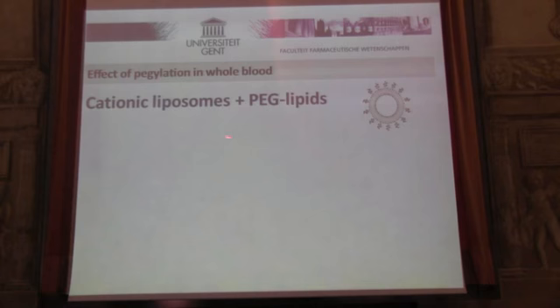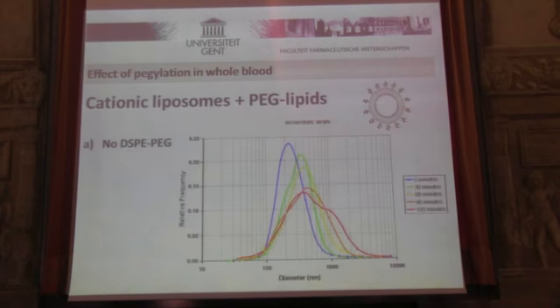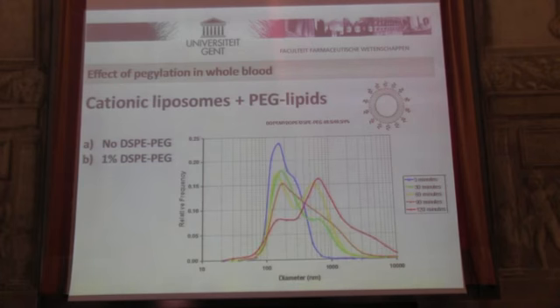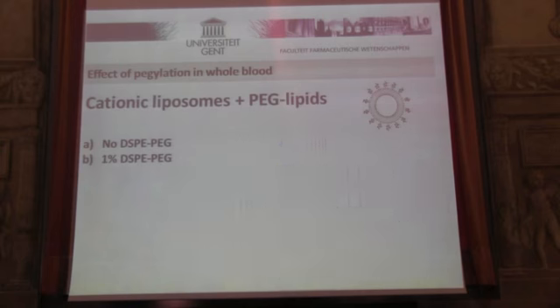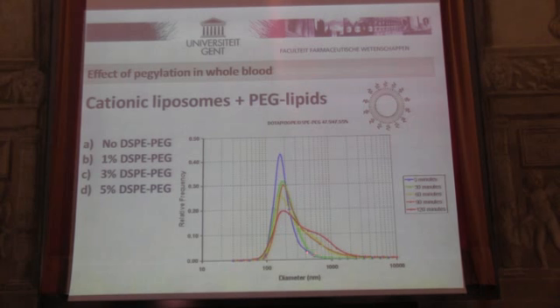So let's move on. We compared with pegylated lipids, with pegylated liposomes indeed. And we were wondering how much of the PEG needs to be included in order to avoid this massive aggregation in blood. So this is the situation without PEG, massive aggregation. 1% of pegylated lipids, no change. 3%, no change. 5%, here something happens.